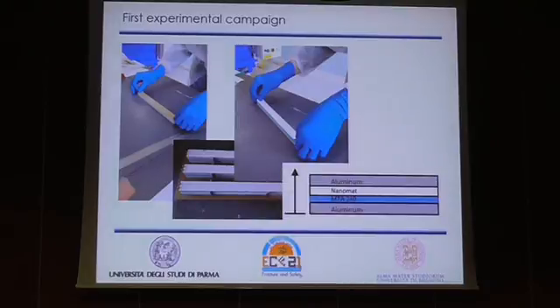In the virgin specimen, MTA 240 Cytec epoxy film was laid down on the first adherent. Then a polyester sheet was used to produce the initial 40 mm long crack. The adherent was placed into a bonding template and the second adherent was put on it. In the nanomodified specimens, instead, after the epoxy film was laid down, a nylon nanomat was stretched out on the epoxy film in order to make it impregnate as much as possible. This is the stacking configuration of the nanomodified specimen.